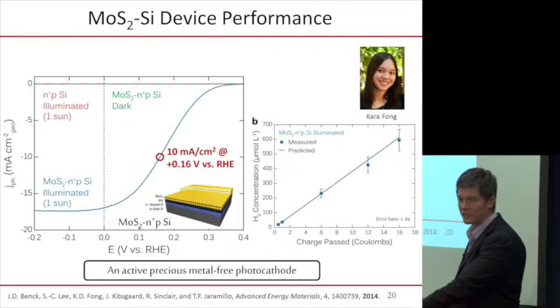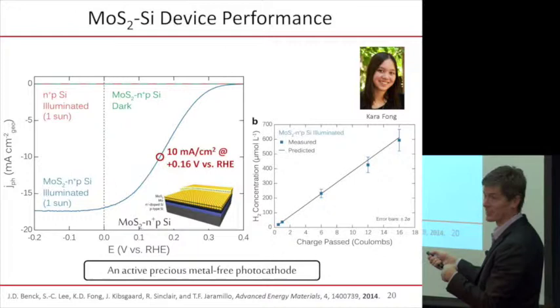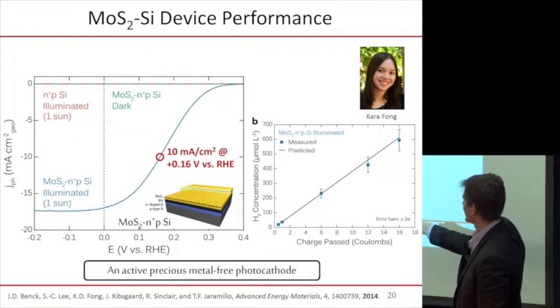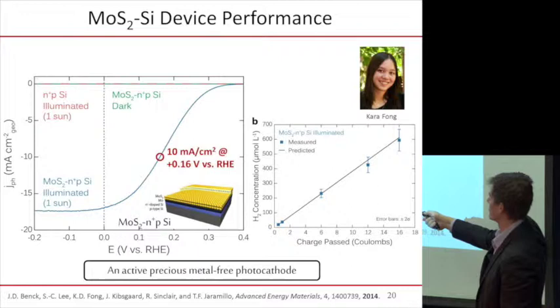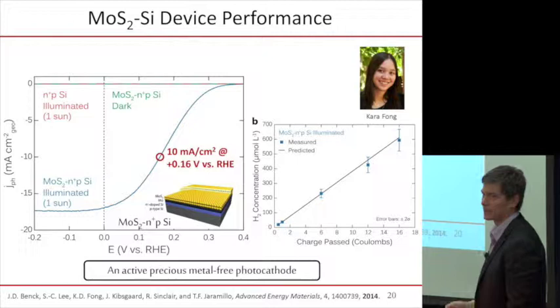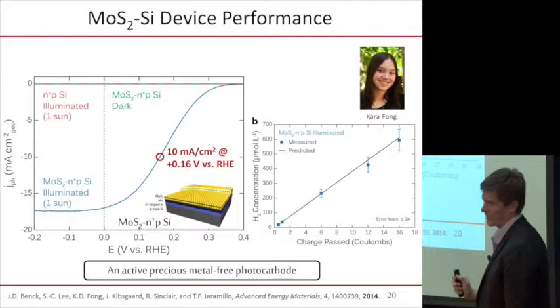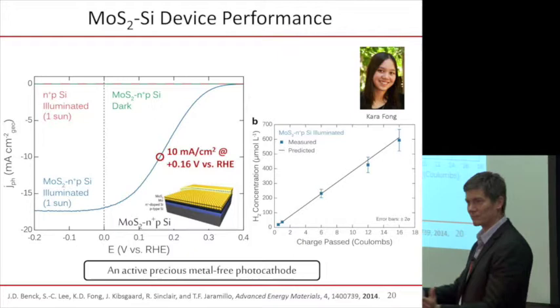But if you shine light onto this system, the silicon is exciting those electrons to a higher state, so now you can actually evolve hydrogen, that's what this current means, to the right of zero. In fact, here we're getting our 10 milliamps per square centimeter at about positive 0.16 volts versus zero on this scale. An undergraduate in our lab, Kara Fong, then did a measurement and showed that 100% of those electrons are actually going to hydrogen. So we don't have any corrosion going on, no funny business. We have just purely selective H2 coming out of our cell.